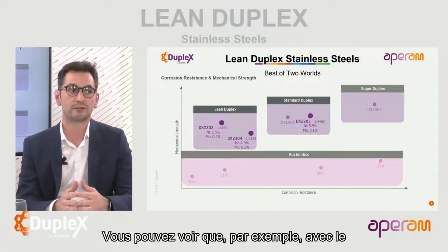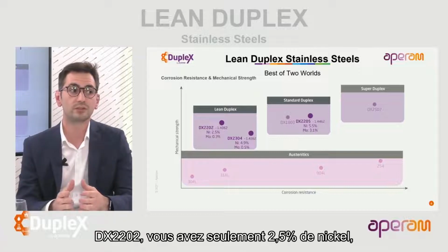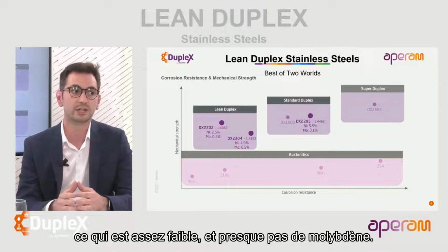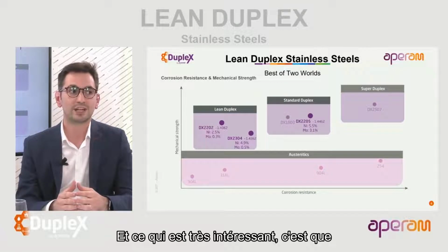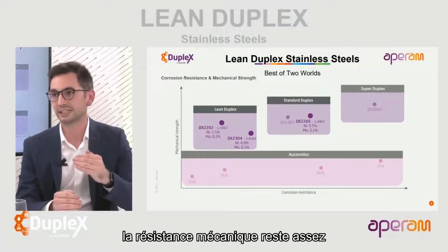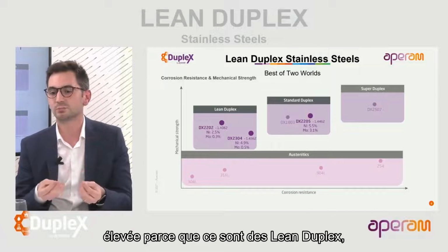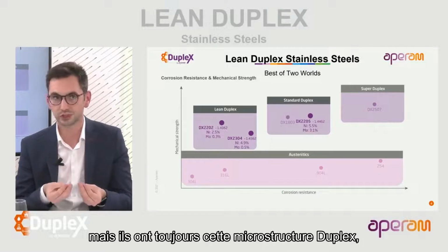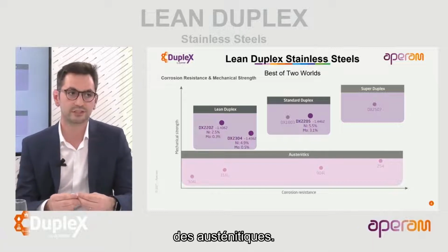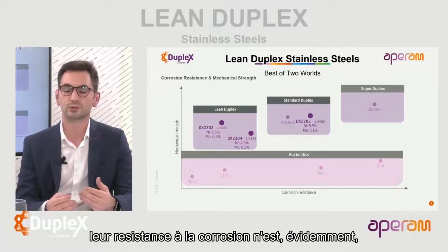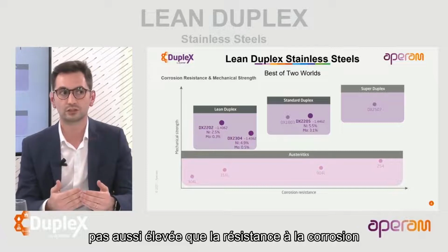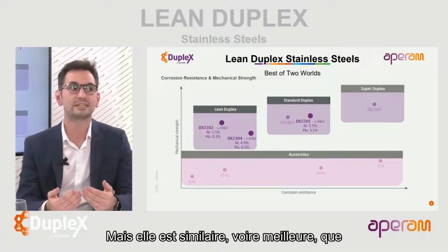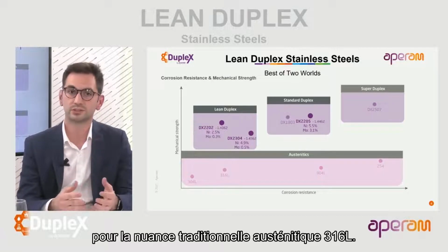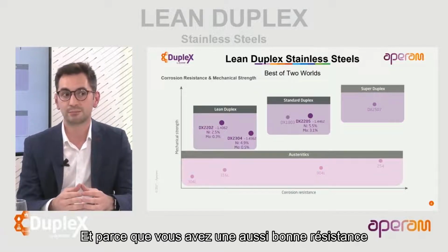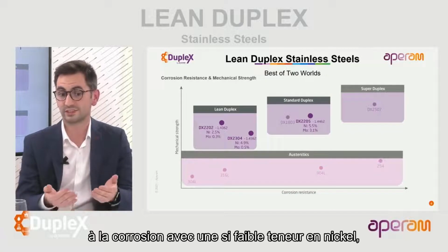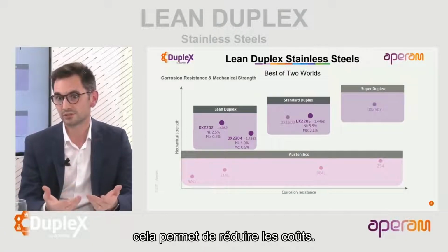You can see that for example, DX2202, you have only 2.5% of nickel, which is quite low, and almost no molybdenum. And what is very interesting is that the mechanical strength remains quite high because these are lean duplexes, but they still have this duplex microstructure, so about twice the mechanical strength of the austenitics. And what's also interesting is that their corrosion resistance is, of course, not as high as the corrosion resistance of standard duplex, but it is similar or even better to the traditional austenitic grade 316L. And because you have such a good corrosion resistance with such low nickel, it allows for cost reductions, of course.